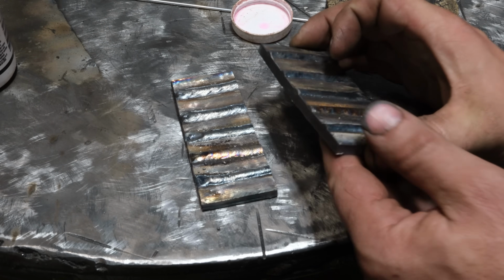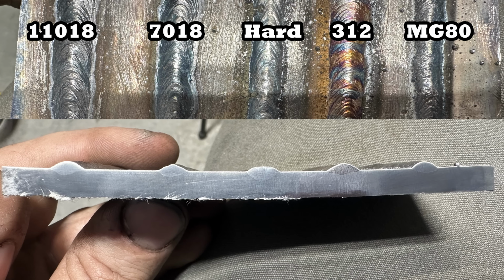All right, got the cut and etch done. Let's take a look at it. So we'll start on the left. The 11018 looks just like a 7018 bead. So mild penetration, not really anything to write home about, pretty smooth bead profile. The 7018 next to it is a little bit rough. That's just that section of the cut and etch, but most of the time it's going to look more or less like the 11018. Now the hard face bead has elements that you don't want to see. So deep penetration, that's not something you want in a flat bead profile.